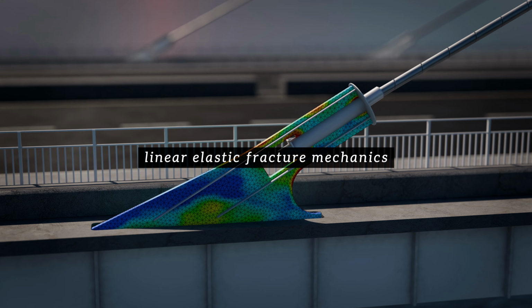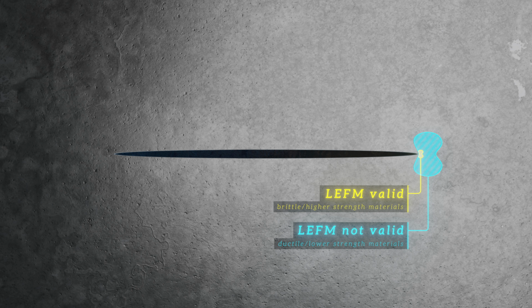We mentioned earlier that the stress intensity factor approach is only valid if the plastic zone at the crack tip is small relative to the size of the crack. This is only really the case for high-strength or inherently brittle materials like titanium and aluminum alloys, high-strength steels, or glass. More ductile or lower-strength materials like lower-strength steels or some plastics deform plastically more easily, resulting in a larger plastic zone at the crack tip, which causes the assumptions of linear elastic fracture mechanics to break down.